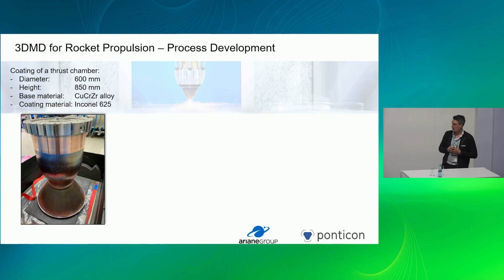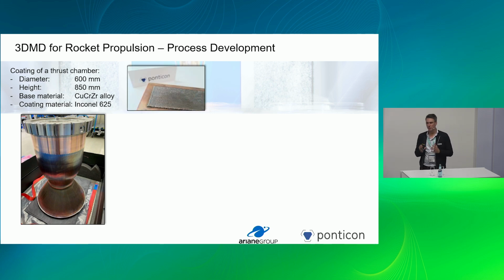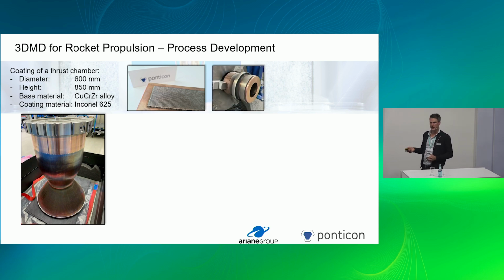How do we typically tackle this? We start with very small coupons where we just evaluate the material combination. Does it stick to the substrate in the first place? So you see this credit card sized copper substrate on this slide with the Inconel coating on top. Then we can also already check for the microstructure, what kind of density we achieve, how the surface looks. So it gives us a very good indication before we get to the next step, which is then a small scale part.